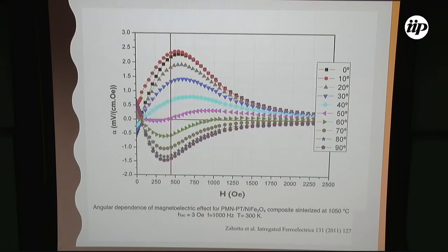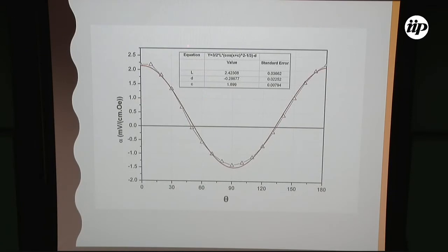It's very interesting: this behavior is exactly the same as, or very close to, the behavior expected from a magnetostrictive effect, using the same expression, 3/2 cosine squared of x minus 1/3, minus d. It is necessary to add these two constants ad hoc because of the coupling of the ferromagnetic and ferroelectric phases. It is a direct action of the electric polarization of the sample, and the magnetoelectric field is a connection with this magnetization.